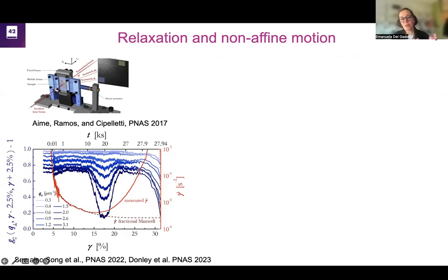So the idea, before I was talking about the history of the system, the stresses that are frozen in. I think if you think about this and the time scale over which the system evolves, and the type of interesting dynamics that the system can have because it has the capacity of storing elastic stresses and relaxing elastic stresses. So what is interesting is that now you can see how, if I start to apply a load or deform this type of material, those regions that were compressed or stretched naturally will not necessarily follow the deformation that I have imposed. And the fact that the system can have regions that can be more or less affected by what happens at the boundary, which is where I'm applying my deformation, will naturally produce a significant amount of non-affine motion.